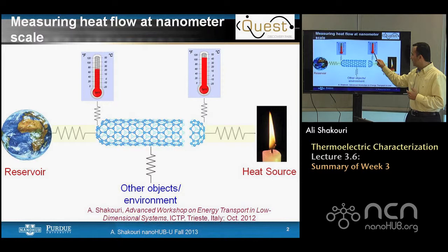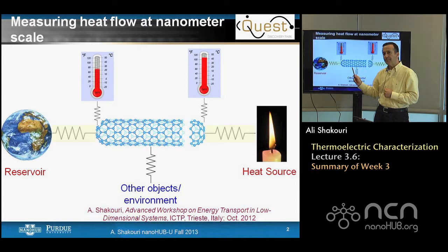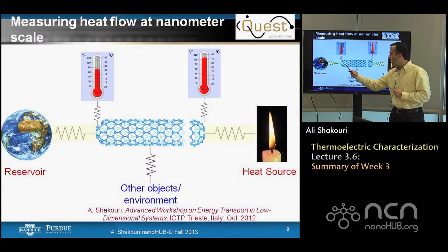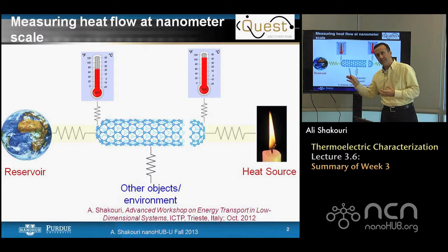Thermal conductivity of materials at room temperature changes by only three to five orders of magnitude, while electrical conductivity of conductors and insulators differs by 20 or more orders of magnitude. As a result, we can confine electrical current precisely and do precise measurements with a good voltmeter. But in temperature measurements, we cannot do that. There are also lots of cross-couplings with the environment, and a reservoir near a nano-object is not a perfect reservoir, so that affects the measurement.